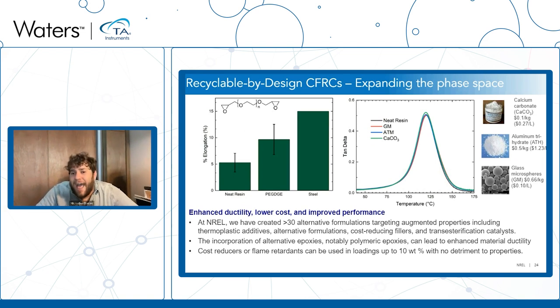Or we can add in additives. And here we can show that when we add in various additives, we can look at the tan delta of the material and we can get no degradation in performance, showing that we actually have a really robust resin.